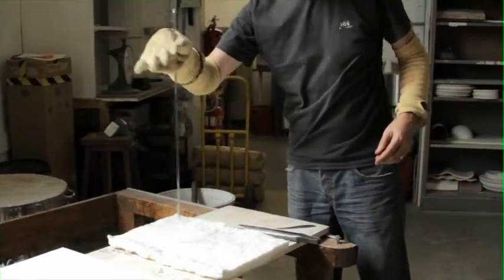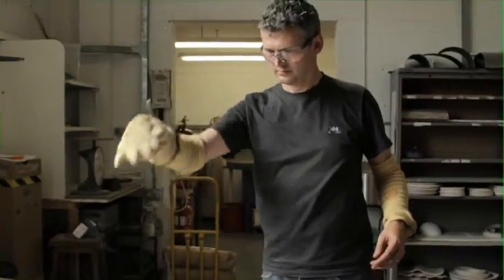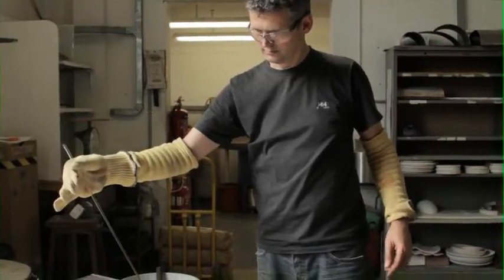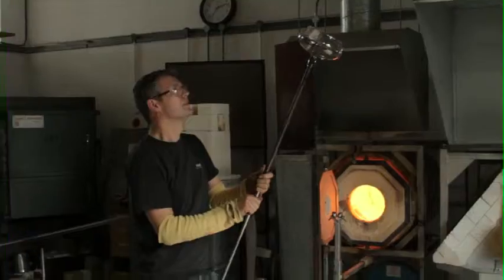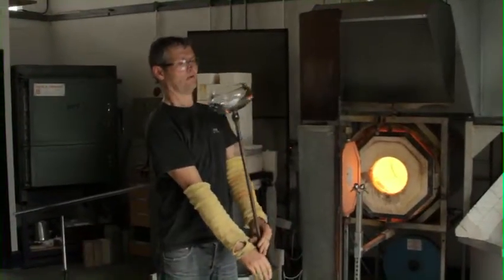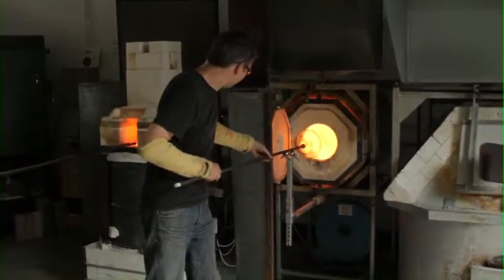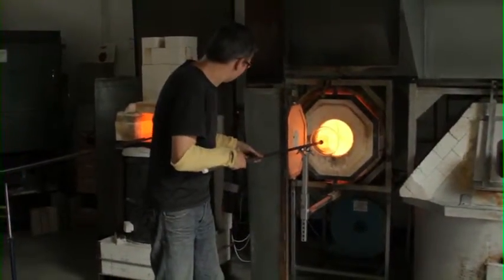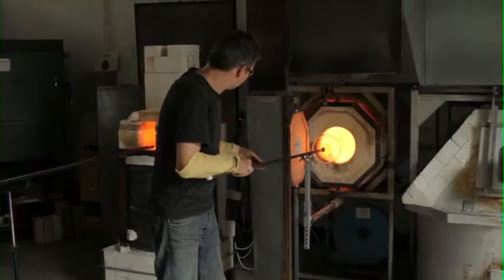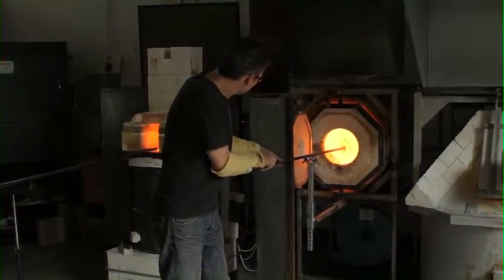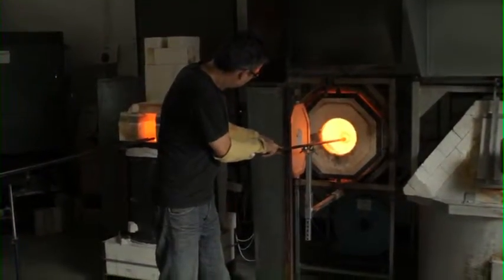I was amazed that the cane slumped at 500 degrees C. More testing gave a softening temperature of 480 degrees C. This in turn gives us a safe annealing temperature of 450 degrees C, remarkably close to that of lead crystal. Now this was quite a shock.